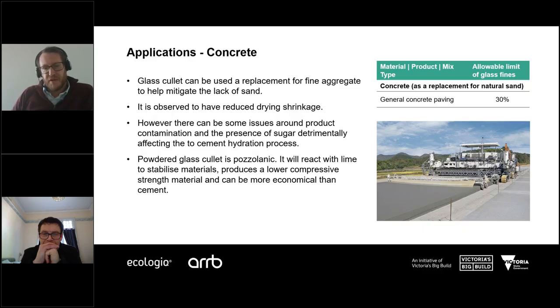In both asphalt and concrete, recycled crushed glass can be particularly useful to mitigate against the lack of natural sand. So in certain areas in Australia, there's a lack of the sand size portion of aggregates, and therefore by incorporating recycled crushed glass we can counteract that lack of natural product and also reduce the amount of virgin aggregate that needs to be mined, and we can also reduce the amount of distance that materials need to be hauled if we've got local recycled crushed glass stockpiles.